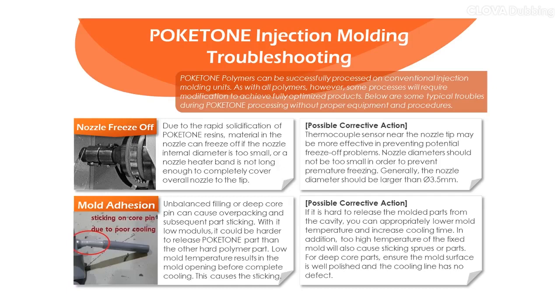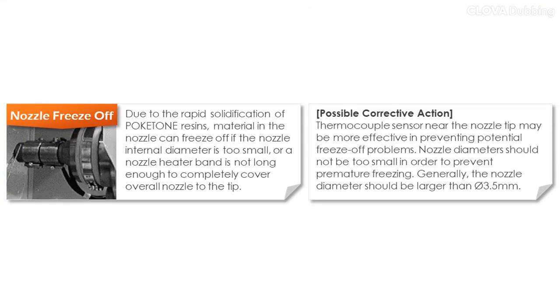This section is about troubles that you may face when polyketone injection molding and corrective actions to solve the issues. We will explain how to avoid freezing of nozzles, how to reduce black specks, and how to deal with unstable metering. Due to the rapid solidification of polyketone resins, material in the nozzle can freeze off if the nozzle internal diameter is too small, or a nozzle heater band is not long enough to cover the overall nozzle to the tip. To handle this issue, a thermocouple sensor near the nozzle tip may be more effective in preventing freeze-off problems. Nozzle diameter should not be too small in order to prevent premature freezing. Generally, the nozzle diameter should be larger than 3.5 millimeters.